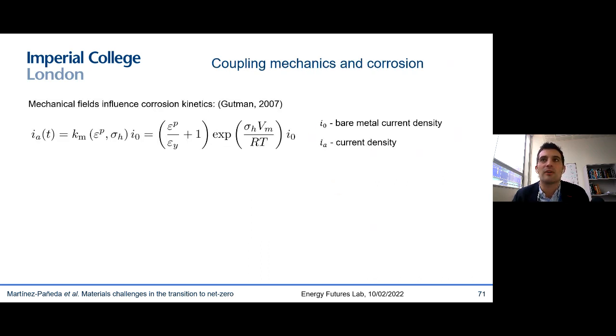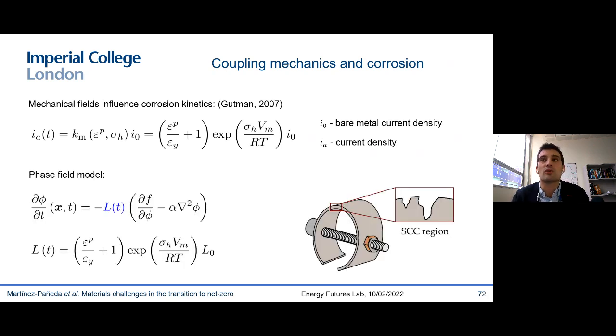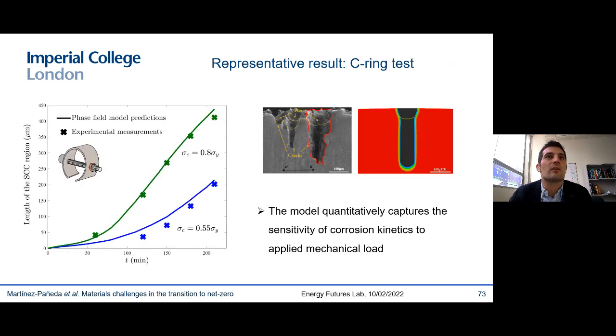And now let me take you briefly to some of the core novelties of our work related to the coupling with mechanics. The first one is the influence of the mechanical fields in enhancing corrosion rates, as argued by Gutman and many others. You can see how the equivalent plastic strain and the hydrostatic stress change the corrosion current density. This can be easily introduced through the mobility coefficient, and we validate our approach by simulating these C-rings experiments that are conducted at different loads. This is the result of our coupled mechanical, chemical corrosion simulations.